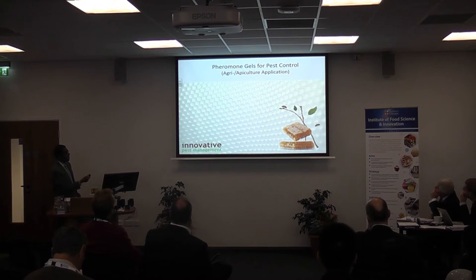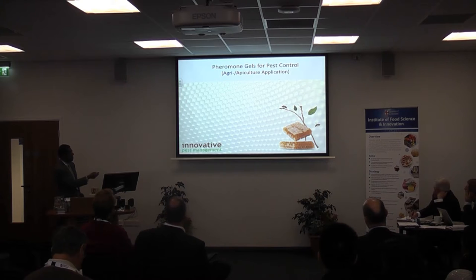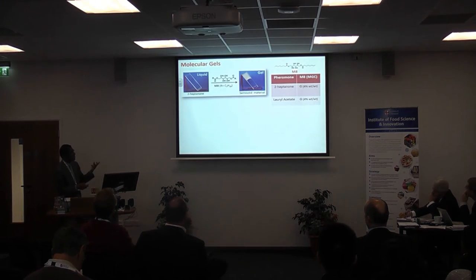And we extended this chemistry to encapsulate pheromones, or any kind of scent molecules or nutraceuticals, because we were working in collaboration with the United States Department of Agriculture. They were looking for a release device for pheromones to increase the production of honeybees, so that they can increase the production of honey, by artificially releasing this pheromone. This is nothing but an organic liquid. We extracted it and we made a gel.